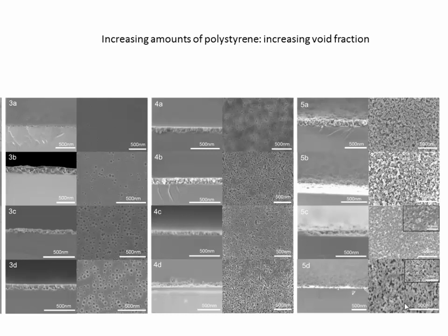When we do SEM, you can see that as you increase the dilution of silica nanoparticles and the amount of polystyrene, you get aggregation of silica nanoparticles at the very end, at the highest dilution and the highest concentration of polystyrene.